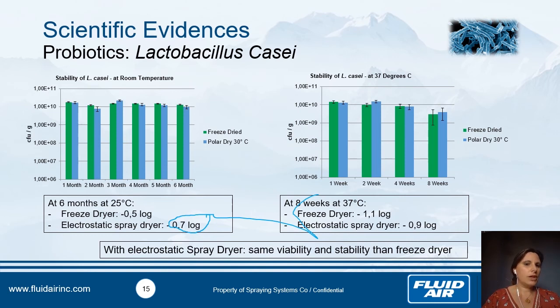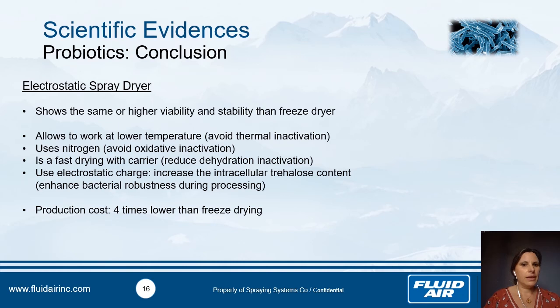We think that by using an electrostatic spray dryer, we have a more perfect microencapsulation. That's why it really helps to have a high shelf life compared to a spray dryer, and we have the same results as the freeze dryer in the case of Lactobacillus casei. So that means that we have the same viability and stability or higher than a freeze dryer. By working at lower temperature using nitrogen, we avoid oxidative and thermal inactivation. We use also fast drying, so we reduce dehydration inactivation. And by using electrostatic charge, we don't kill the bacteria, the probiotics.